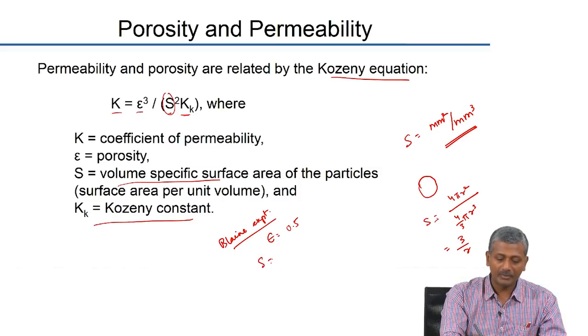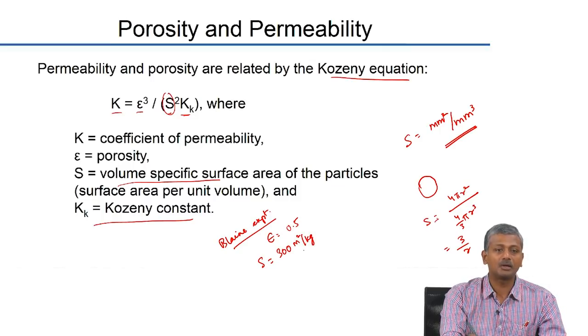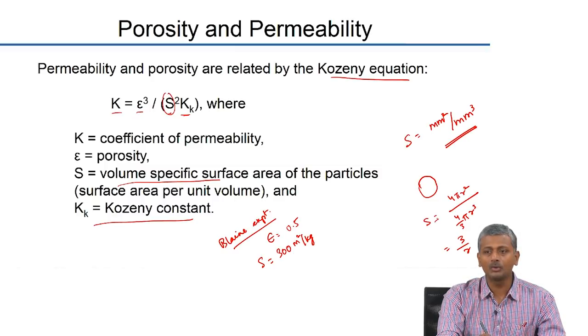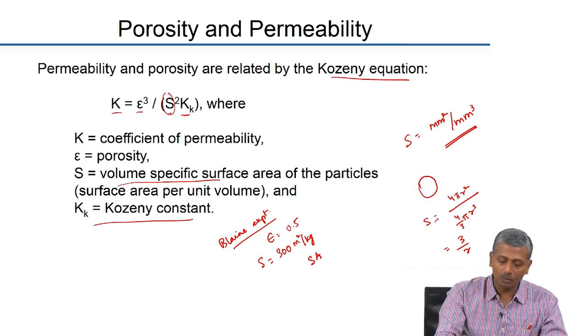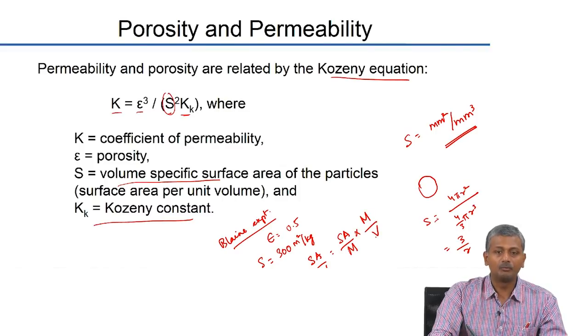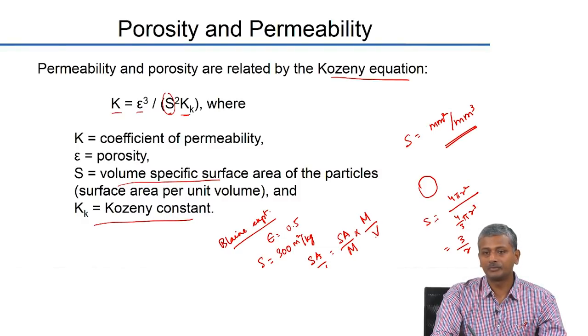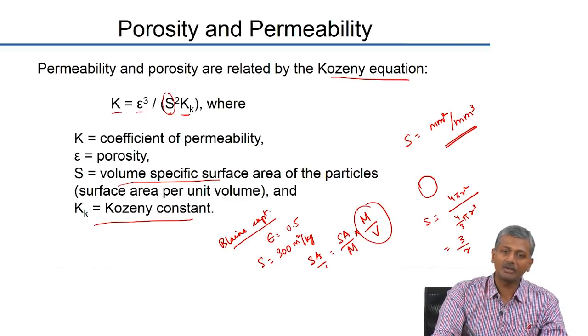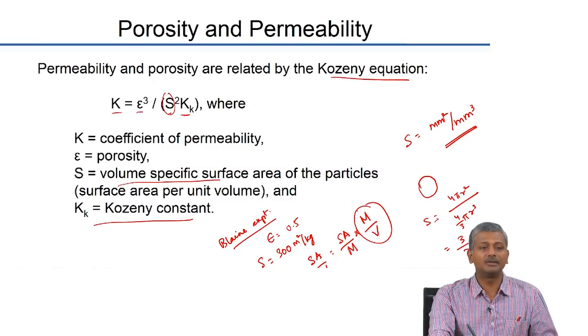Your surface area for cement, what is the surface area typically? 300 square meters per kilogram. But that is the mass specific surface area, right? You need to convert that to the volume specific surface area. How will you do that? So surface area per unit volume is equal to surface area per unit mass multiplied by mass over volume, right? But then you have porosity in the system, right? So your volume is different. This is not exactly your density, because density is mass of solids by volume of solids, but here you have porosity in the system. So you need to convert that to an equivalent mass over volume, okay?